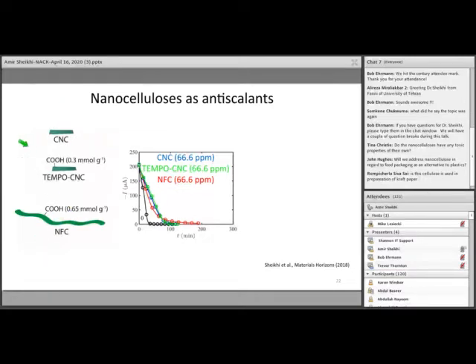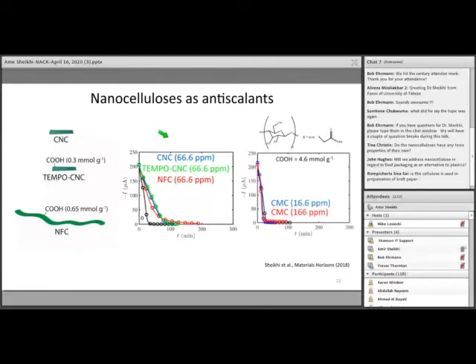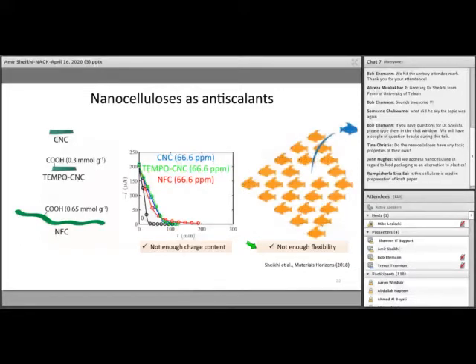nanocelluloses. Don't forget that our competitor is the phosphonated industrial anti-scalant, which is effective in our condition at less than 10 ppm concentration. And here you can see that 6 times that concentration doesn't have that much effect. Then I thought maybe the problem is the charge content. So what we did was to use carboxymethyl cellulose with more charge on it, but the scaling result is still not good. And the reason for this is because these conventional nanocelluloses don't have enough charge on their surface, and this fully solubilized cellulose chain does not have enough structural flexibility.